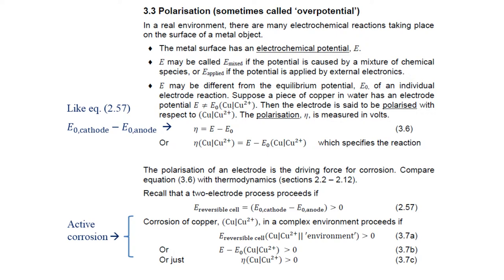So if we recall equation 2.57, which said that a two-electrode process is thermodynamically predicted to go forwards if the reversible cell potential is positive, meaning the difference of the cathode equilibrium potential minus the anode equilibrium potential. If that's positive, as shown in equation 2.57, then we predict that the reversible cell potential is positive and the corrosion process will proceed with whatever metal is there at the anode.